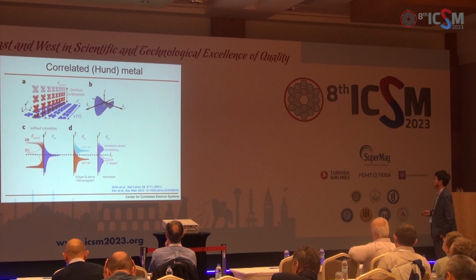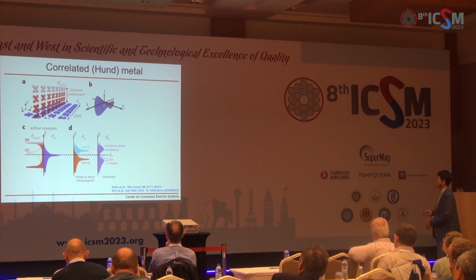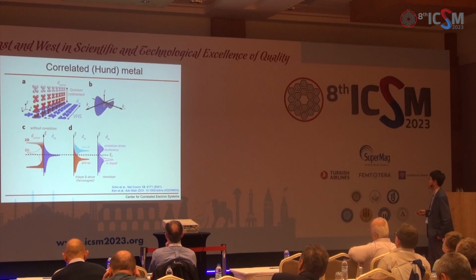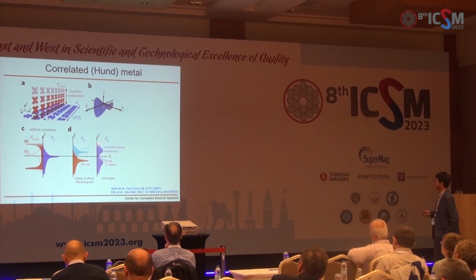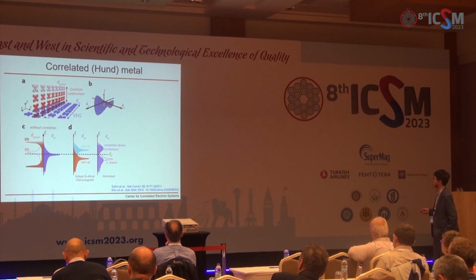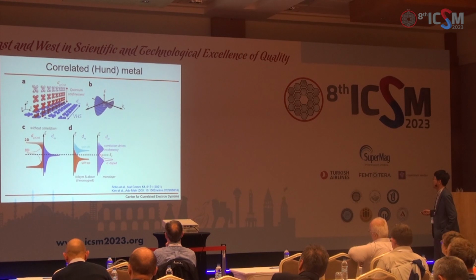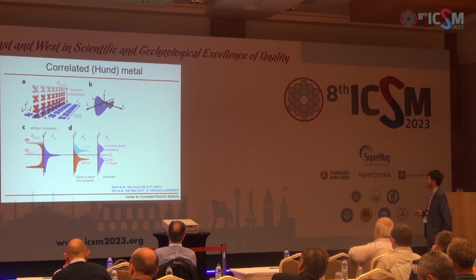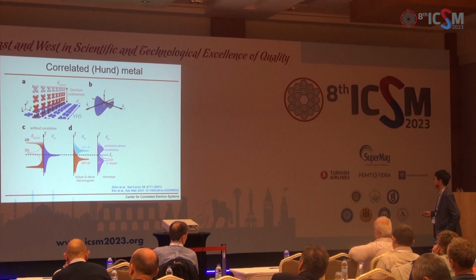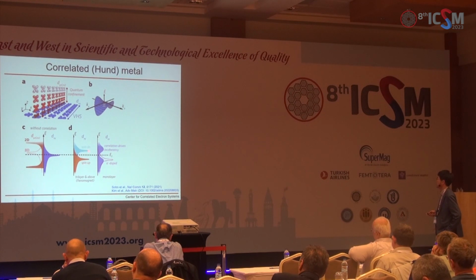Now let's focus on this xy. That can go in 2 directions. One, again, ferromagnet, spin up and spin down. That's how you lower your density of states at the Fermi level. Or another path is that this is correlation-driven, basically you go into a Mott state. So what's happening for our case is that there's a correlation-driven incoherence. So this is very close to a Mott state, but with a very small Fermi edge. So not quite a Mott state, but it's fairly close to a Mott state. We call that correlation-driven incoherency, and calculation shows that that's actually a metal.